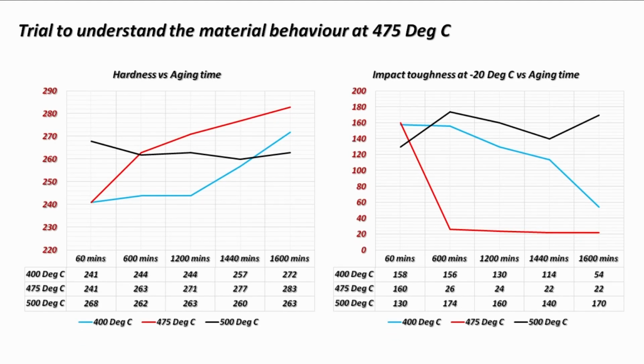Now further we took some other test blocks and heat treated them at various temperatures like 400, 475 and 500 degrees Celsius, and tested for hardness and impact toughness. We can see the hardness of the material at 475 degrees Celsius drastically increases, indicating the material forms this alpha prime phase at 475 degrees Celsius with highest kinetics. However, the impact toughness falls suddenly to 26 joules from 160 joules. Whereas at 400 degrees Celsius, we can see a linear drop in the impact toughness.